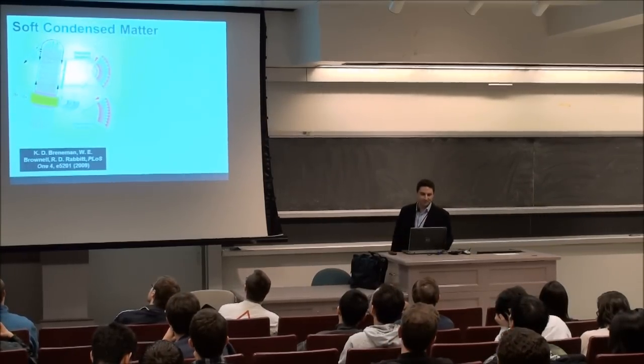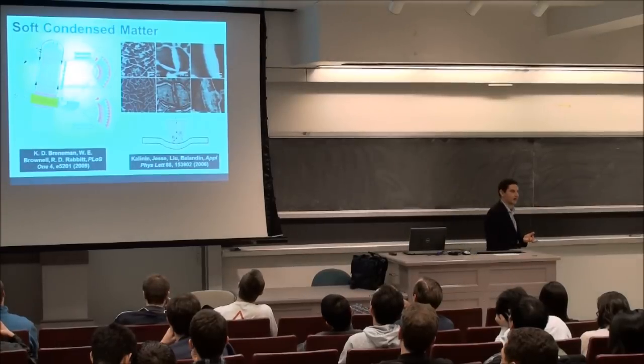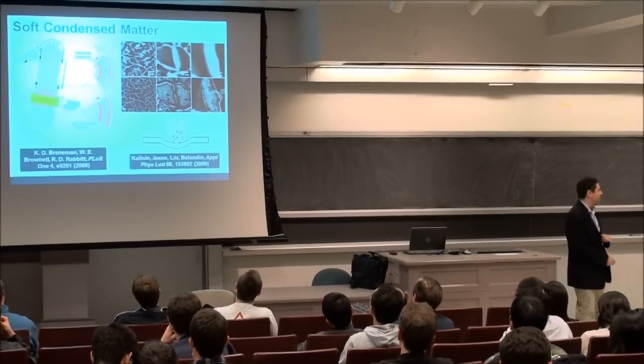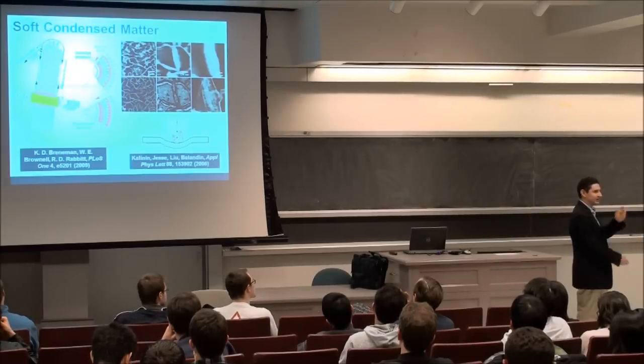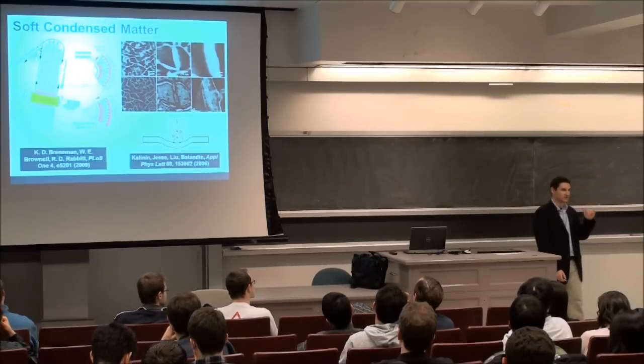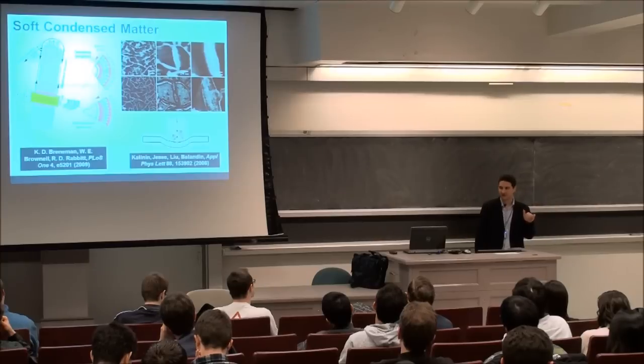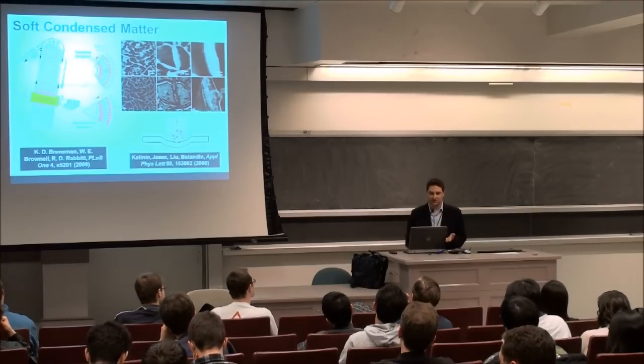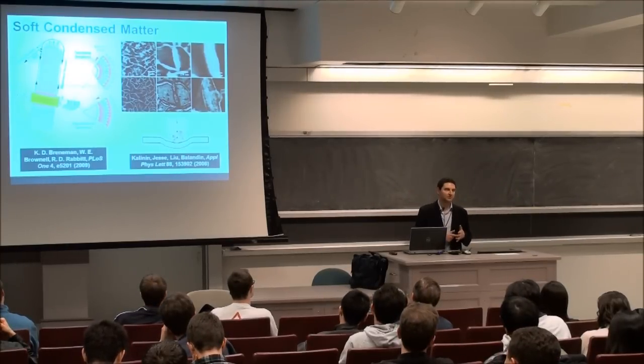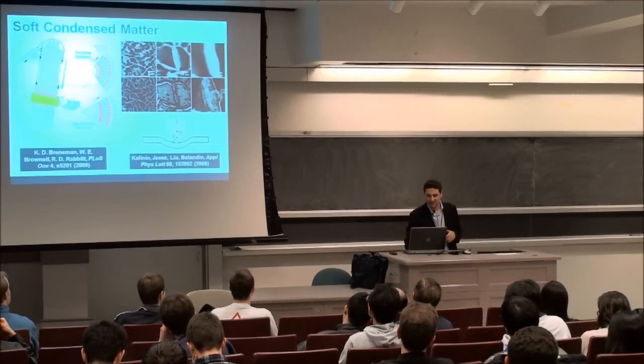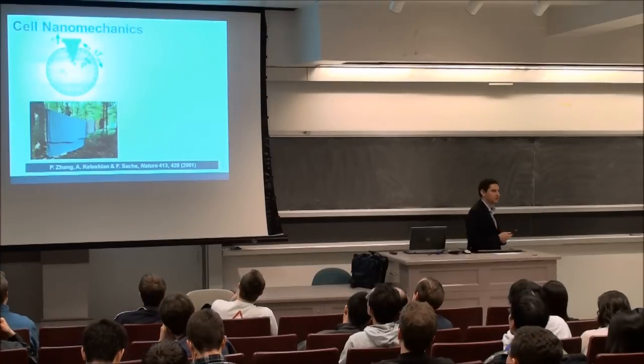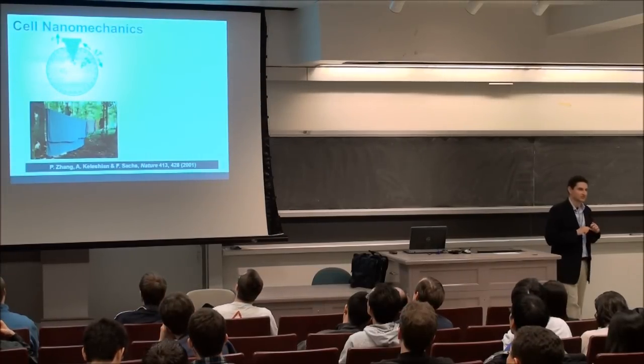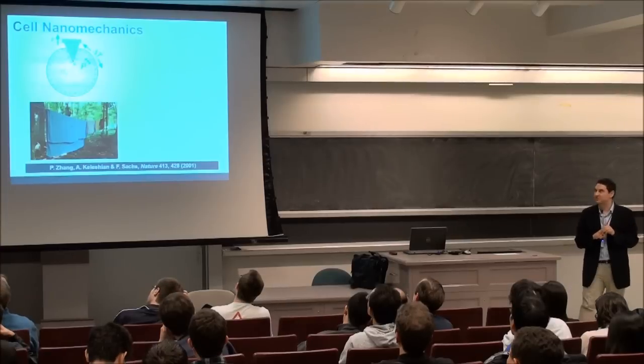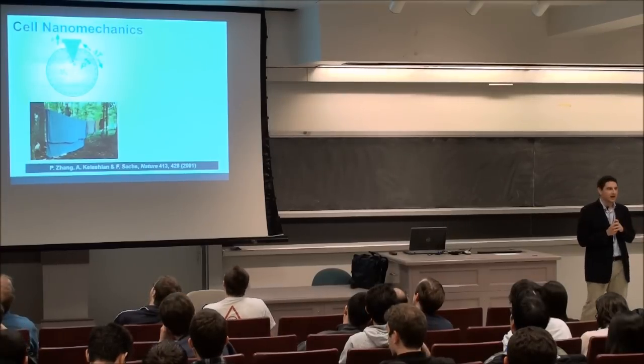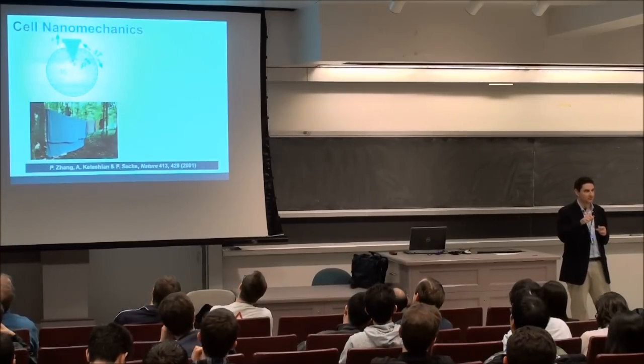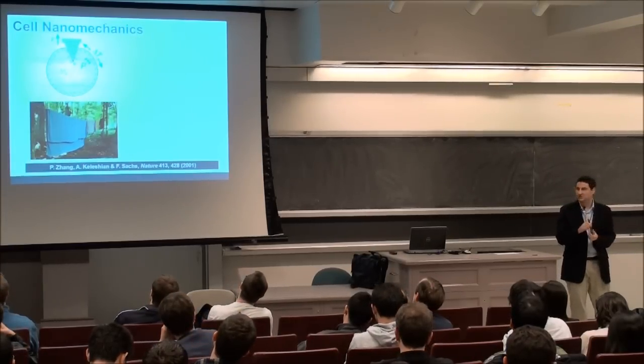Who knows? But there's been some work also at Oak Ridge where they looked at tobacco mosaic viruses. They can probe the piezo response in these viruses, and they can see that there is a flexoelectric effect of about 10 picometers per volt, which I think is fascinating. But we had this idea that maybe you can measure this flexoelectric effect in cells using our piezoelectric nanoribbons. If you look at what people have done in the past, they've taken AFM probes and probed them into cells and depolarized the cells here.